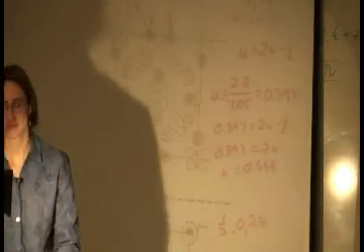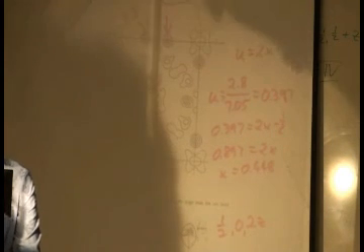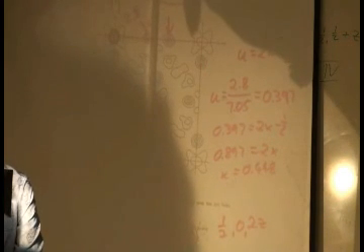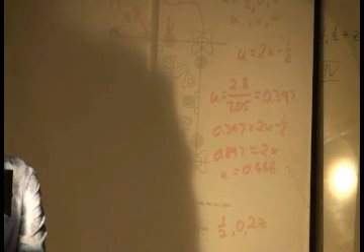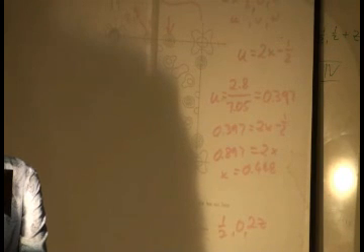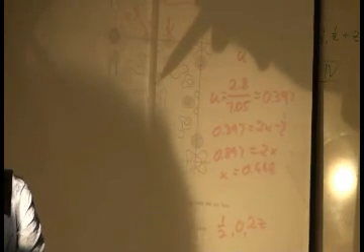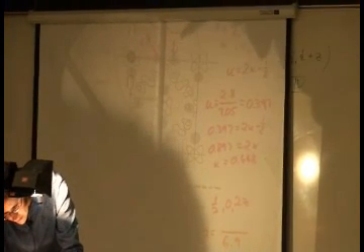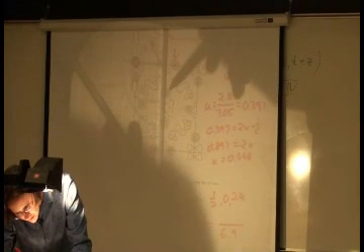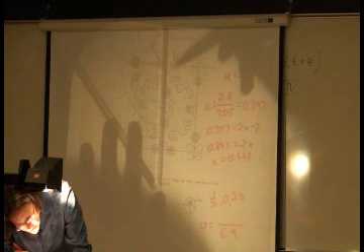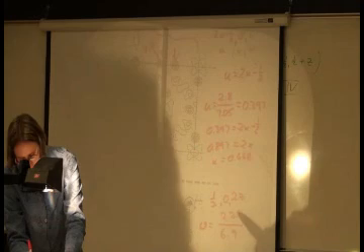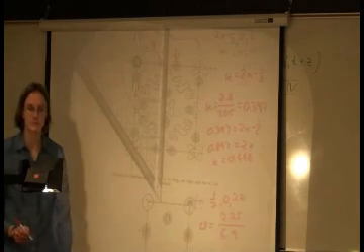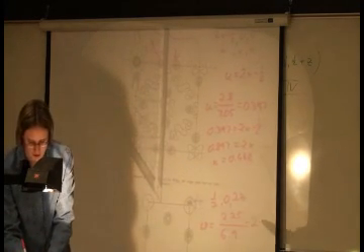How do we approach it? Same way. We need to measure what the total distance is. And that would be 6.9, okay? And if we take that peak up here, then that would be about 2.25. And that will be equal to 2x.